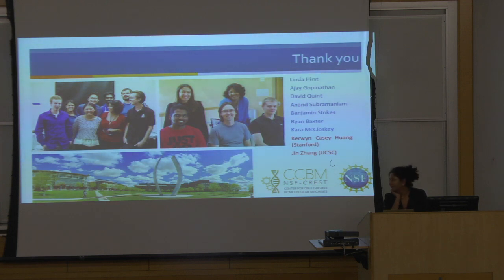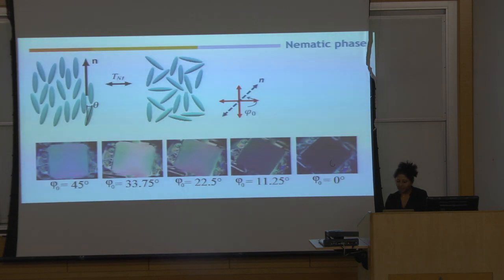Yes. How does it change from one liquid crystal to another? Oh, it's a change of orientation. So I think this is one type of liquid crystal. Some of them can change with pressure and other things too. So this one, as we increase the temperature, if it's disordered, we cool it down, it will give some sort of positional ordering. Orientational ordering. This is the nematic phase. So just by changing temperature, it can go from liquid crystalline to the liquid phase, and back, and so on.